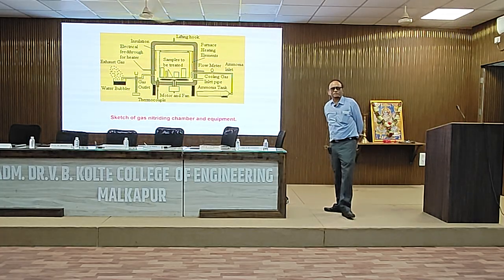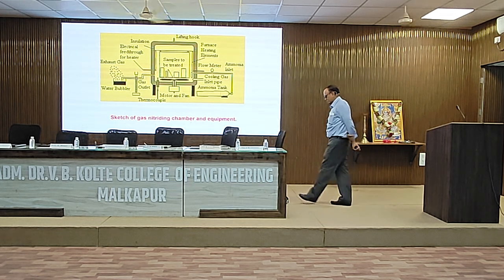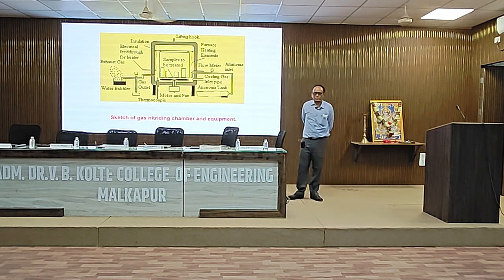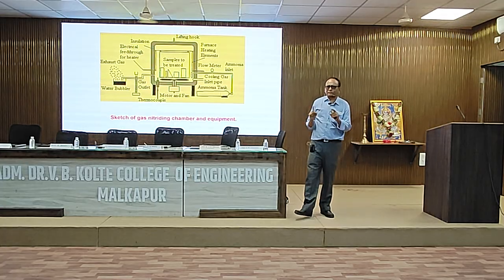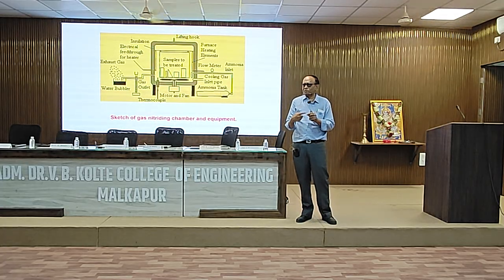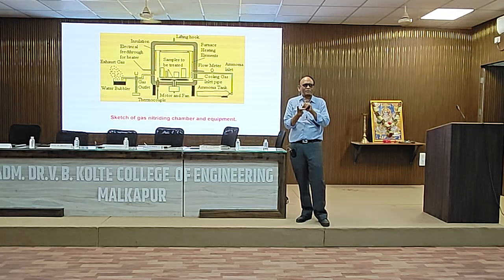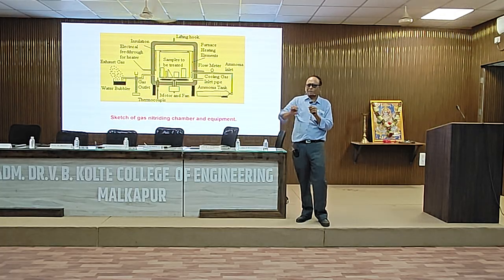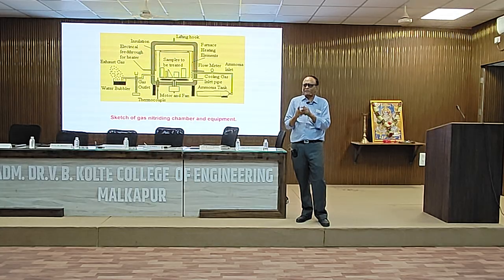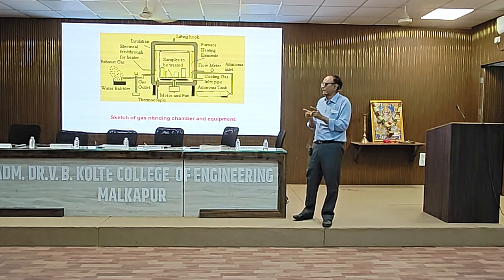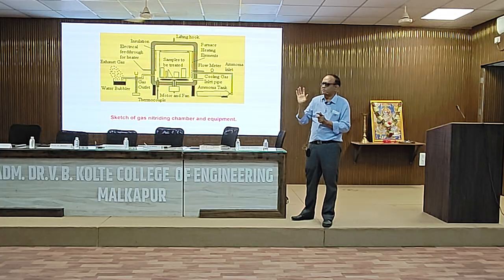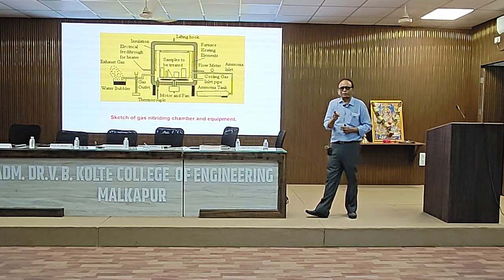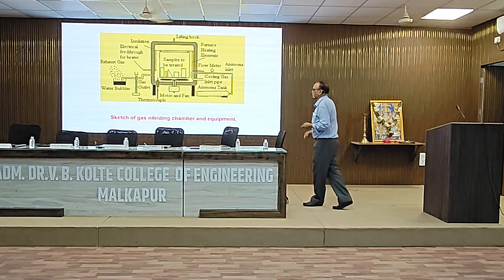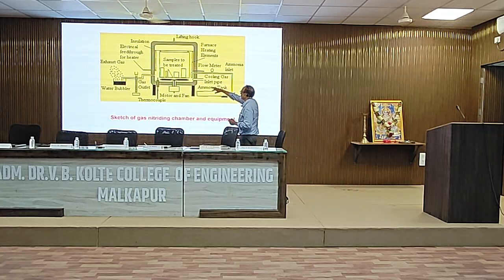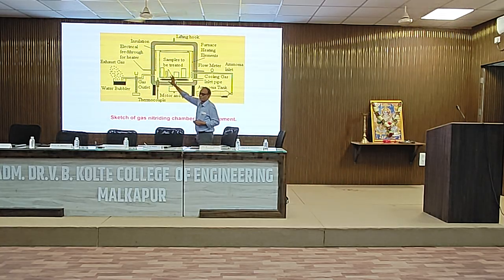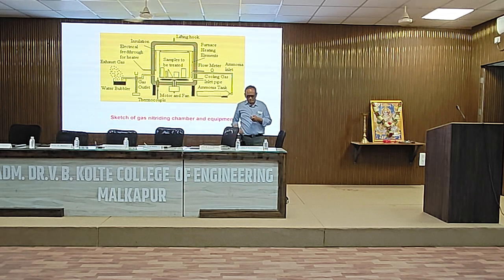And when there are two phases, there are two crystallographic phases having two different coefficients of thermal expansion. So when you are in service, like when you are cutting something with this nitrided component, the two phases will expand differentially because they have different coefficients of thermal expansion. That will develop cracks, and because of this crack generation, there may be peeling off of the nitrided case. So that is why your objective is to get a single phase, and getting a single phase in the nitride is not possible by gas nitriding, but by plasma nitriding.